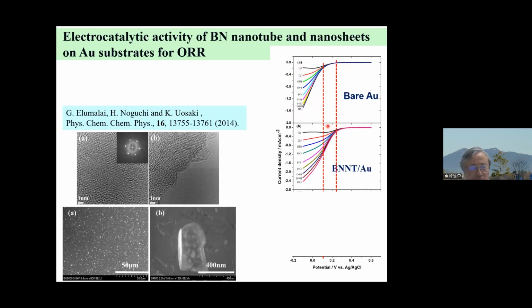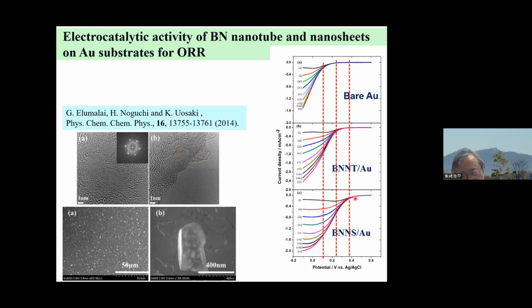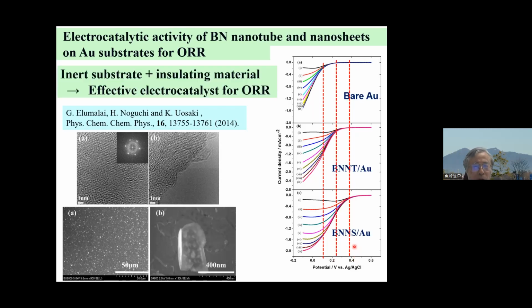Then, since boron nitride nanotube does not have good contact with the substrate, we used boron nitride nanosheet. These are the nanosheets, and you can even see the atomic fringe. The boron nitride nanosheet is much better than the nanotube and far better than bare gold. It's more than a 250 millivolt shift. So we demonstrated that, of course, gold is very bad as a substrate, and boron nitride is an insulating material, but the combination of both gives an effective electrocatalyst for oxygen reduction reaction.